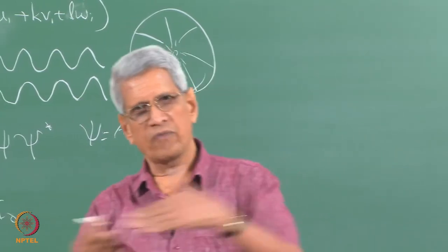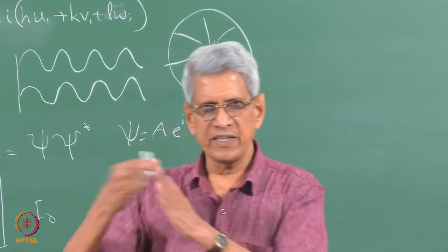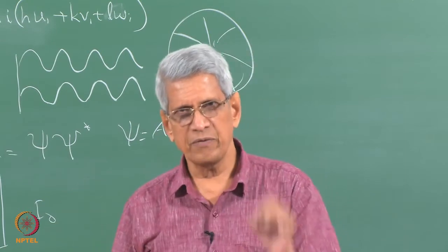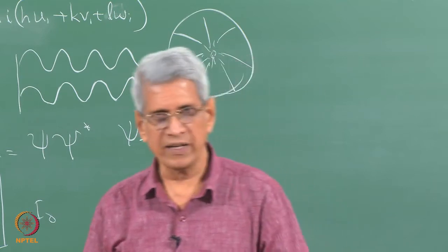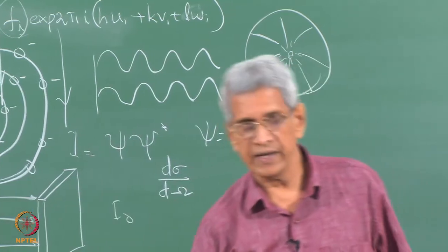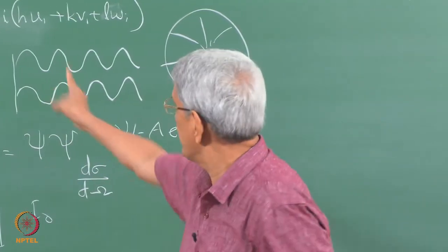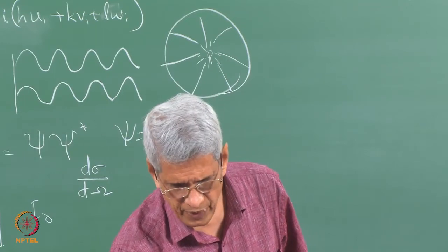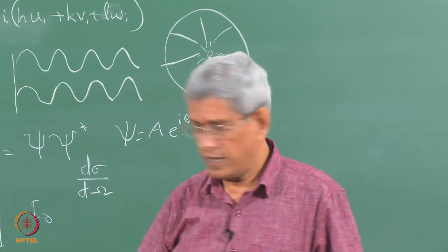Whereas in the case of electron scattering, in the forward direction, as the angle of scattering changes, we find that there is a change in intensity. Then we should know how it is changing as a function of angle. Then we have to use the term differential cross section, which is generally written as d sigma by d omega. Omega is the solid angle which we take on the surface of the sphere which we consider. As an example, if you consider it, this is what I have done.